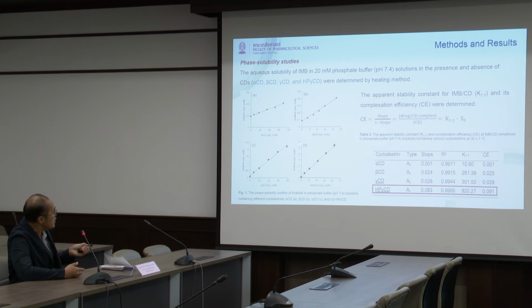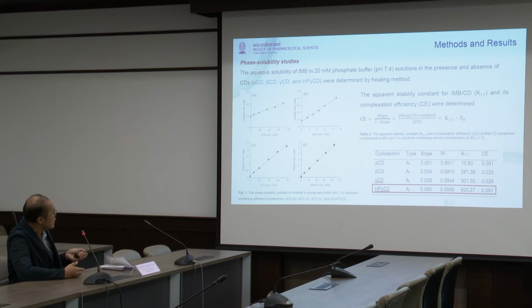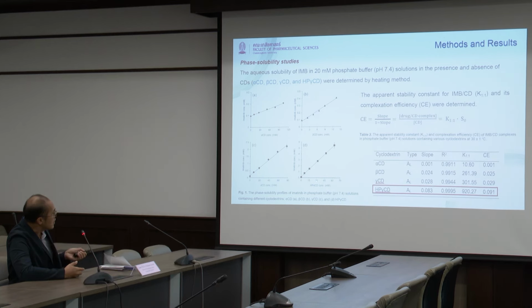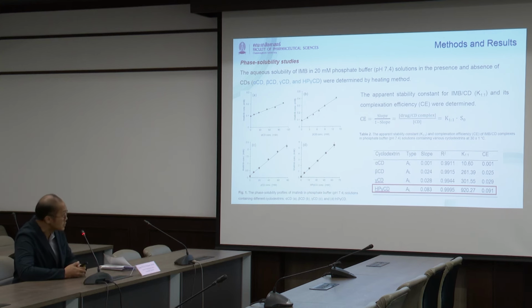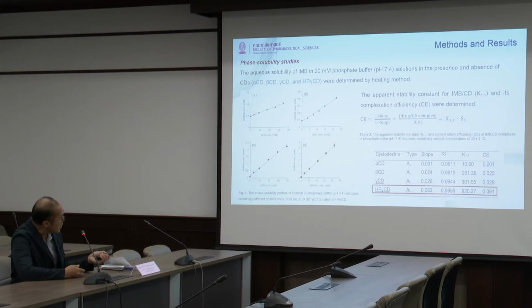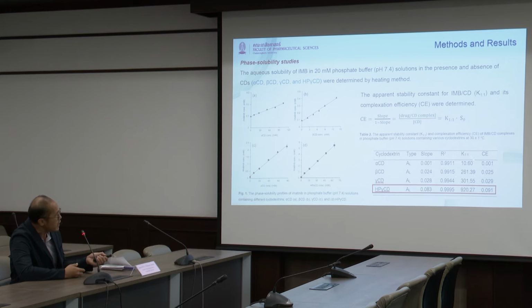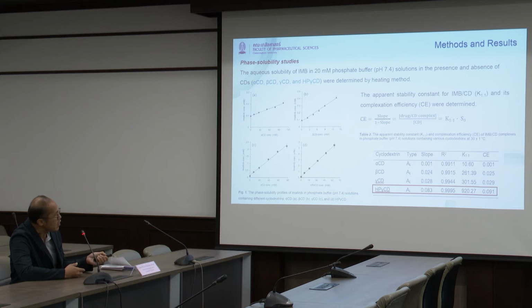Then we show the figure: when we increase the concentration of cyclodextrin, the solubility of imatinib increases. Among the natural cyclodextrins, gamma cyclodextrin is the best one, from the largest cavity, which gives complexation efficiency and stability constants higher than beta and alpha. And hydroxypropyl gamma cyclodextrin, the derivative one, is the highest. It is the best solubilization.